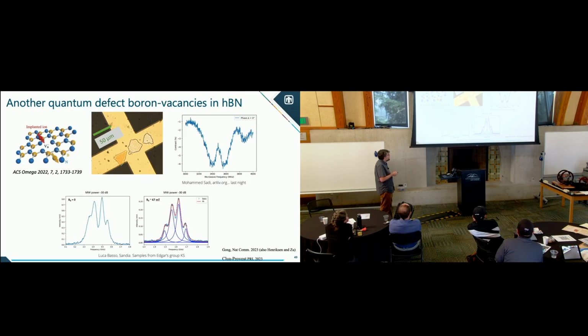So even though we can't exactly isotopically enrich them out, we got a sample that has, I don't remember which isotopes exactly, boron 11 and nitrogen 15. And since the nearest neighbors to this boron vacancy are 3 nitrogen spin 1/2, that gives you the total spin 3/2 states, and you can see 4 peaks from the neighboring nuclear spin states here. But this is sufficiently more narrow that we can actually look at DC type sensing, or similarly do T1 and T2 type sensing with this material. And now you have the power of exfoliation, where you can put these 2D sheets of hexagonal boron nitride with boron vacancies onto other things, like other materials of interest.